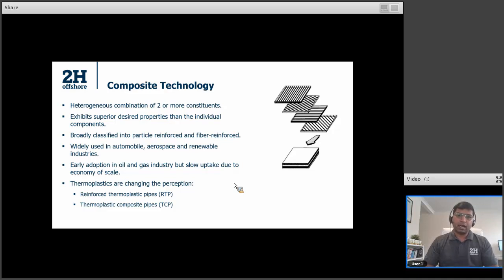And these fibers can be aligned in different directions to provide strengths in whichever direction that we want. For example, if we need more strength in axial directions, we can get that by varying the inclination of the fibers. And vice versa, if we also need more strength against the pressure, we can also change the orientation of these fibers to get more strength against pressure. So composite technology gives us more control on the manufacturing process, helping us to streamline the technology to suit the required field conditions.